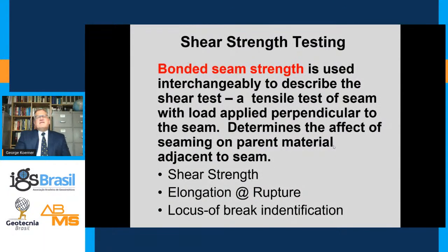This is very different than the shear testing of the material. This is the type of stress that the material would see in the field. You again are looking at 25 millimeter wide specimens. You're testing them and looking for a shear strength, an elongation at rupture, which has to be greater than 50% typically, and then a locus of break identification in that regard.